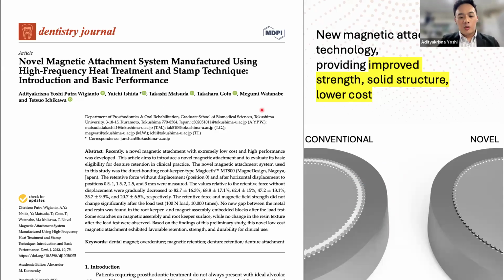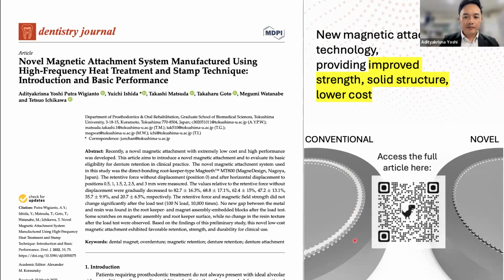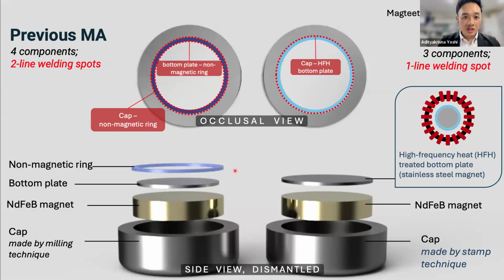Therefore, in 2022, we researched a new magnetic attachment system with a new structure, resulting in improved strength and a solid structure at lower cost. As you can see here, the laser welded structure has been reduced by half, only 50%, which minimizes the risk of deformation of the joint structures seen in the past. These are the structural comparisons with the previous magnet assembly, which was composed of 4 components. To connect these 4 components, 2 laser welding lines are required. With the technology of high frequency heat treatment, we can merge 2 components into 1. This technology resulted in fewer welding spots, only 1 welding line.